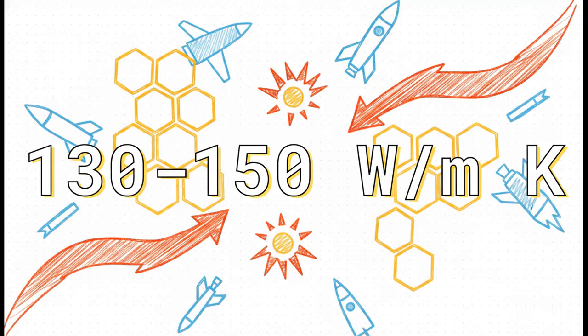And while it's surviving all that intense heat, it's also incredibly good at moving it. We're talking approximately 130 to 150 watts per meter Kelvin. That is massive in-plane thermal conductivity for bulk HBN, making it an exceptional heat-spreading material. It pulls those intense thermal loads away from your most critical components incredibly fast.